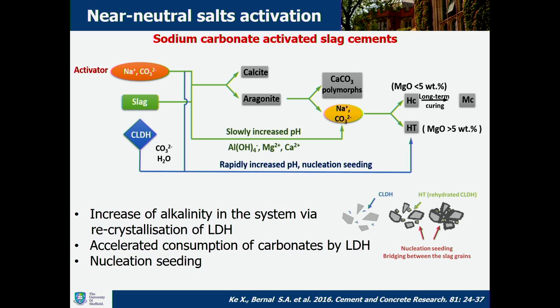So after a lot of hard work, a lot of discussions, a lot of thinking, we came up with this schematic mechanism of reaction when we use sodium carbonate activator. In this case, we can see that we favor formation of the different polymorphs of calcium carbonate. If we have very low contents of magnesium, we will form hemicarbonate or monocarboaluminate at later age of reaction. If we have high contents of magnesium within the system, we will favor formation of layered double hydroxides.